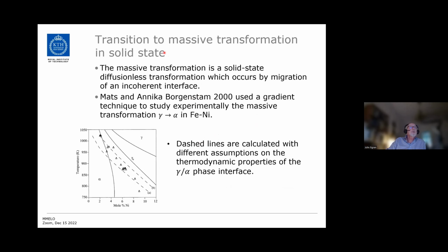So we can look at this also in the solid state. In the solid state, we have what is called the massive transformation. It is diffusionless, and it occurs by migration of an essentially incoherent interface. So it is different from the martensitic transformation, which we will come back to. And Mats and Annika Borgenstam in year 2000 used a gradient technique to study experimentally the massive transformation from austenite to ferrite in iron nickel. And the symbols here are their experimental results. And you can see, of course, they fall below the T0 line. Otherwise, it would be impossible. But they also fall in the two-phase field, because there were many discussions at that time whether it could fall into the two-phase field. And those dashed curves are calculated using different assumptions about the properties of the phase interface.